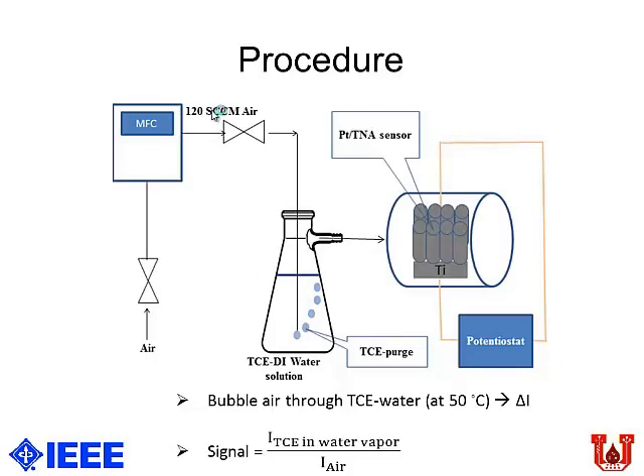This is the lab setup, to prove the proof of concept. What you have is air as a carrier gas, passed using a flow controller to control the flow rate, and then your baseline is just passing air through your sensor, which gives you the baseline current. After some time, air is cut off, and instead it's passed through your sample, which is trichloroethylene in DI water at different concentrations, ranging from 0, which means there's no trichloroethylene, to 1000 ppm trichloroethylene water. So air at 120 SCCM is purged as a carrier gas. It carries your trichloroethylene water vapor with it to your sensor.